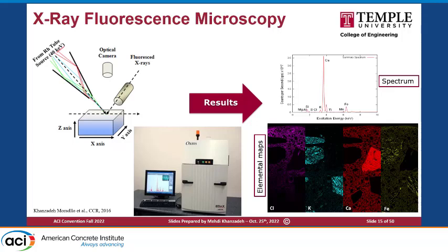This is a surface technique, so with a small amount of polishing, you don't need to use any coatings. You can put really large samples underneath this display, and you can image it, this raster you are seeing. For example, you can get the chloride map, the potassium, calcium, and so on and so forth. Then you have these elemental maps from this X-ray technique.